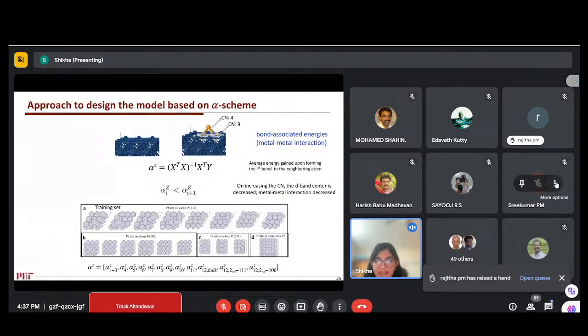So what we do is basically create a training set where we will change the coordination number of the site, and we will pick different surfaces to have good statistics of the coordination number. Then we will calculate the site binding energy from the given training data set. Now we need to predict the bond associated energy, like the energy of the bond when we add a metal atom to the surface. Then for each bond, like we have the coordination number 4 or 9, what would be the energy of the ith atom formed when we add the atom to the surface?